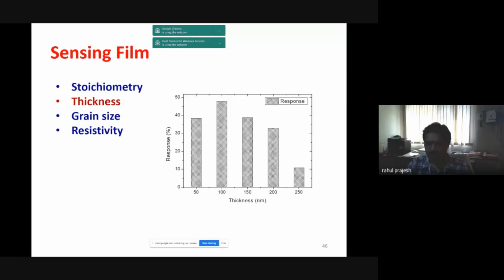In the sensing film, what are the important parameters? First is stoichiometry. If you talk about SnO2, the stoichiometry of these two components, Sn and O, is very important. This will decide your complete sensing performance. Another point is thickness. You need to understand the optimum thickness you should deposit so that you get the maximum sensitivity. According to what I have observed, 100 nanometer to 150 nanometer is the best sensing thickness you should deposit. If you go for 2D materials, you can deposit even lower thickness and get a higher response. What I'm talking about is for thin film.